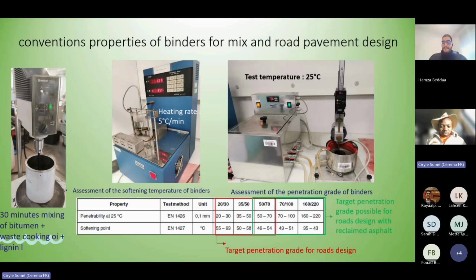This test is performed at 25 degrees, and the principle is to allow a needle subjected to a mass of 100 grams to penetrate the bitumen. If the bitumen is harder, the needle doesn't penetrate deeply. And if the bitumen is very soft, the needle will penetrate deeply into the bitumen. Those two tests allow us to classify the bitumen.